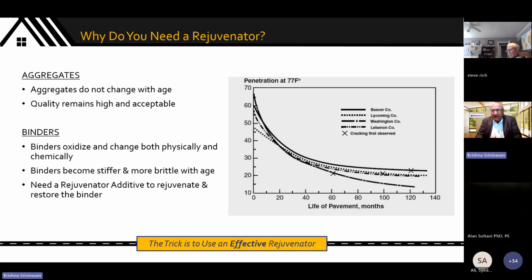There is often a case made that, well, through SARA analysis, you need to replace the chemical constituency. And in fact, some data, not all, some data has borne this out. When you add 1 kilogram per ton of mix, you're not rebalancing anything from a chemical standpoint. What you're doing is altering the rheological characteristics, the failure characteristics, which could be rutting, which could be cracking, could be fatigue, anything. That's really what you're changing with modern day rejuvenation philosophy.